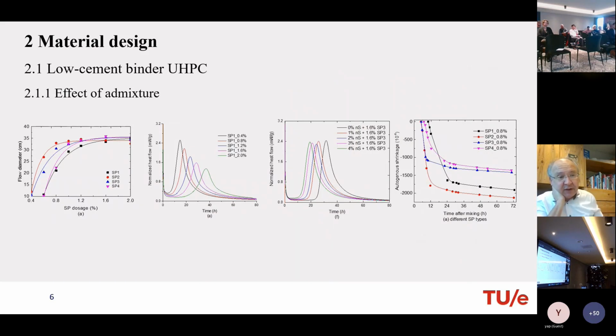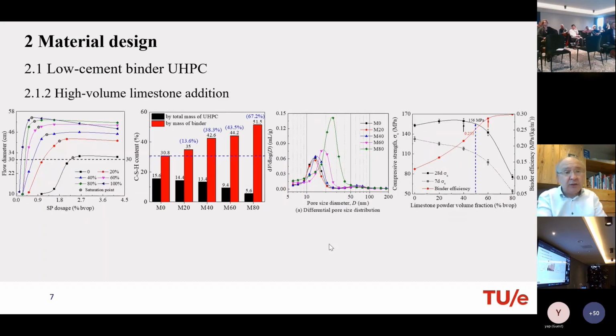We looked at the effect of SP dosage on flowability. So you can see that different SPs have different saturation points, where further addition does not help in spread anymore. We looked at the effect on hydration, there are calorimetric results, and also after mixing and so on. Considering the time, I will not go into details.